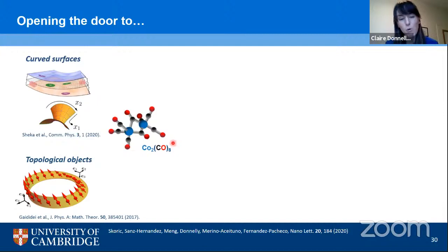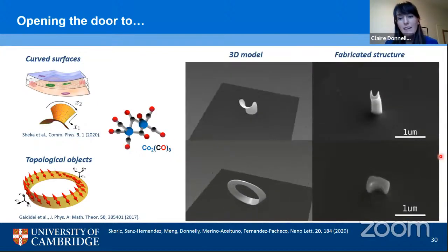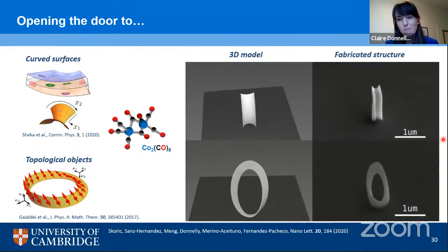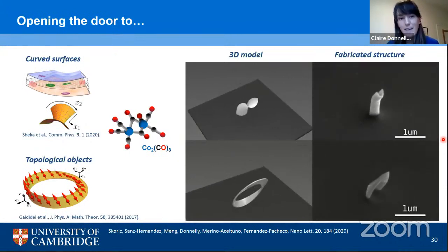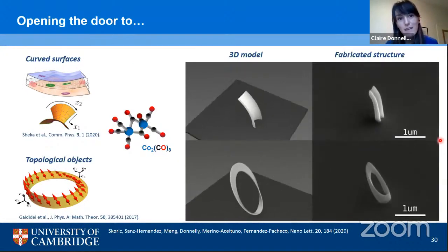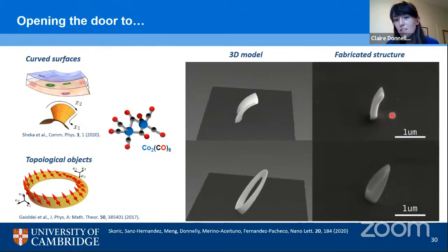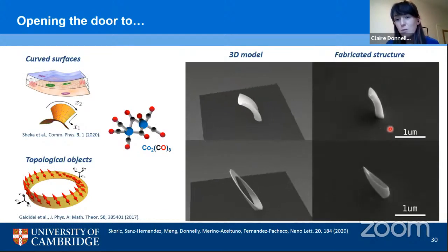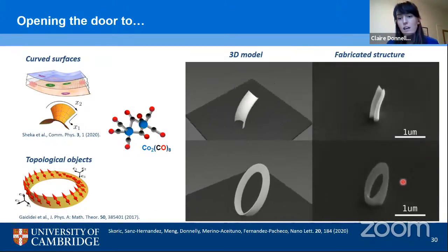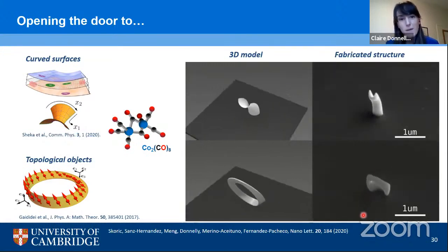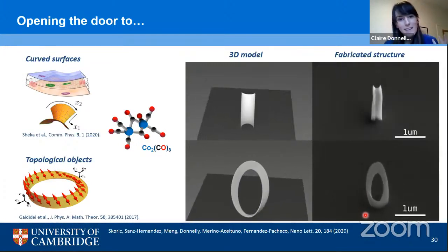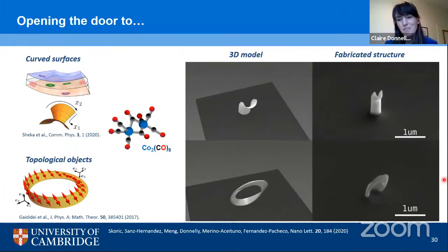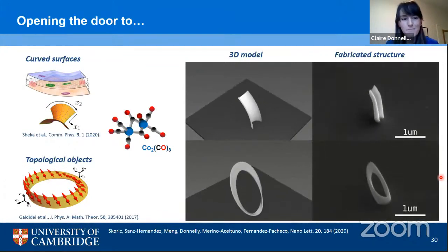So taking inspiration from these two examples, Luka went on to fabricate these structures with cobalt FEBID, and in this way has been able to demonstrate really nice examples of 3D magnetic nanostructures, ranging from these curved magnetic systems, which have both positive and negative curvature, to what we believe may be one of the smallest Mobius strips, and definitely one of the smallest magnetic Mobius strips that has been realized to date.